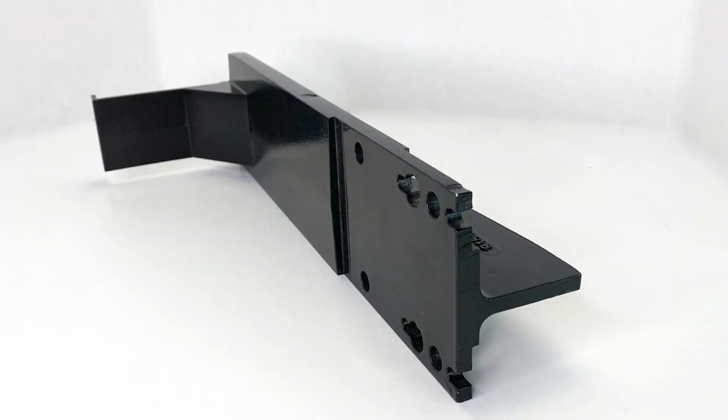If you're looking at anything below 1/4 inch wall thickness, you're probably looking at either die casting or even a different process, because when you start getting into casting, you need a specific wall thickness to start filling in. For a design to be manufactured with permanent mold casting, you need that 1/4-inch, pretty much 250 thousandths, wall thickness so that you can get a solid fill.